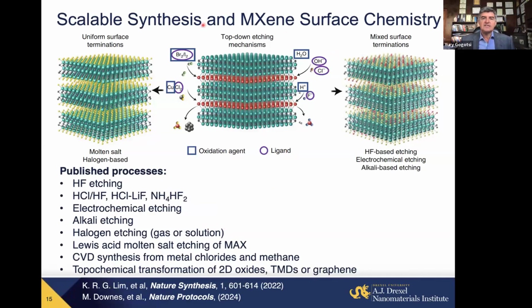That if we start with MAX phase synthesis, the first method developed, we can etch it in acids. It can be hydrofluoric acid, that's what we started with, but it can be a mix of different acids. For example, hydrochloric acid with metal fluoride, sodium fluoride, lithium fluoride. You can do it electrochemically, alkaline, many others. But you also can use molten salts, chloride salt mix, or gases, for example, chlorine. You can also do CVD or even transform two-dimensional oxides or chalcogenides or graphene into MXenes. So there are many ways to make it.